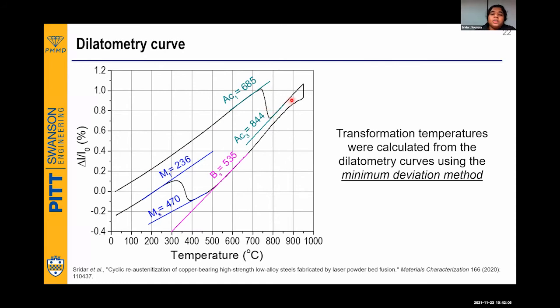And again, it keeps increasing, and then you have some waiting time, either 1 minute or 40 minutes. Then it drops down, and you start cooling at 100 Kelvin per second. It's going to go, and there is a slight slope change, which corresponds to the bainite start. BS here corresponds to the bainite start temperature.